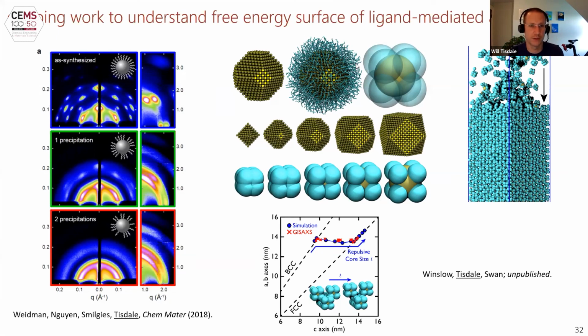Just that difference in compressibility or the elastic properties along one particular facet versus a different could lead to this ordering behavior. And this is what Sam is trying to model here in this coarse grain representation of a quantum dot, where he has different ligand spheres with some characteristic interaction potential that is bound to different facets of the nanocrystals. But yeah, at some level, it has to be the facets. Ligands alone won't give you any particular epitaxial orientation.